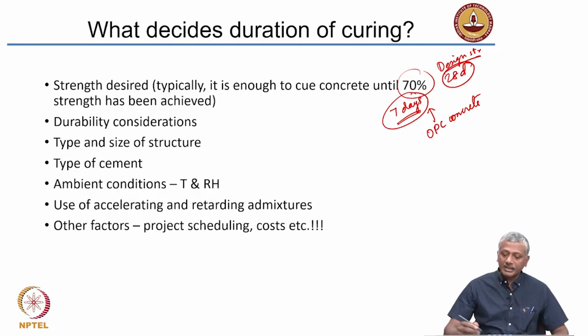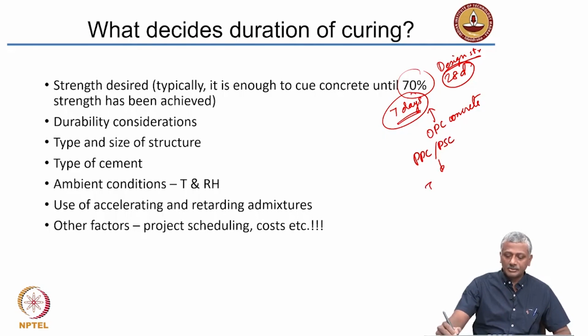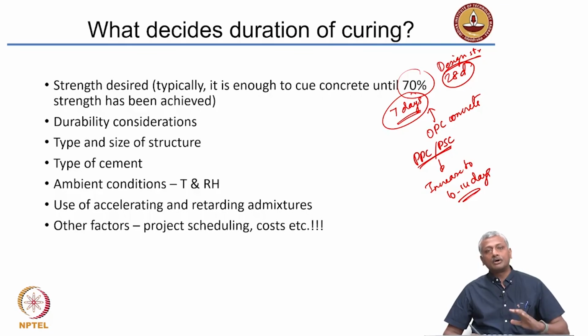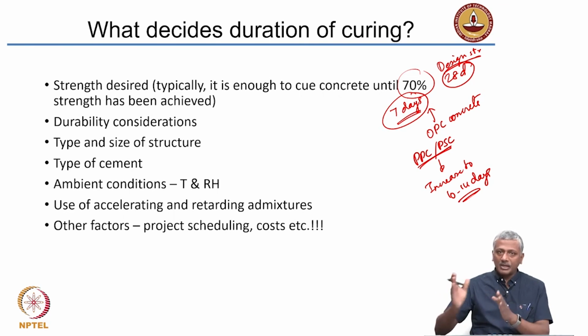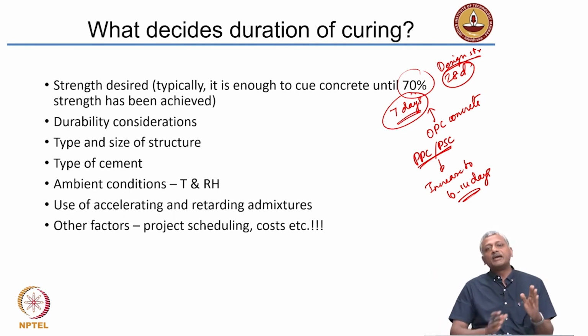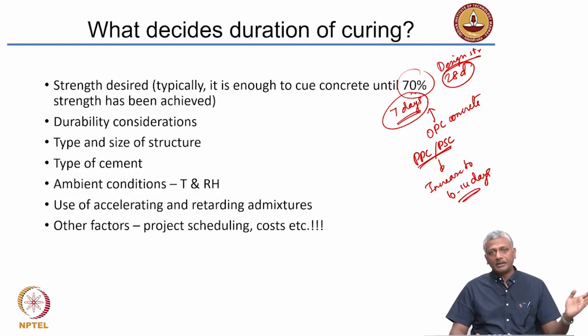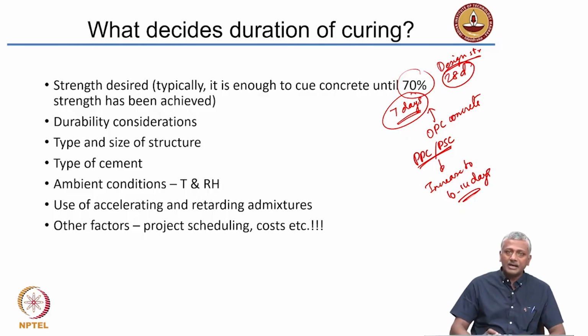Okay. But when you are using PPC, Portland Pozzolan Cement, or PSC, this curing duration increases to 10 to 14 days because these cements will be slower to reach the strength level of OPC. Okay. So please remember, the use of blended cements like PPC and PSC leads to stronger and more durable concrete in the long run. But to get there, you need to ensure that the curing duration is increased as compared to OPC. Okay. So you need to cure for longer to attain the same level of performance at the early ages, but that will guarantee you a much better performance in the long term.